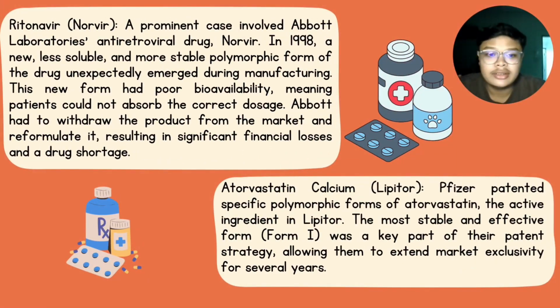Now, I will give the real-life examples. First, ritonavir. A prominent case involved Abbott Laboratories' antiretroviral drug, Norvir. In 1998, a new, less soluble and more stable polymorphic form of the drug unexpectedly emerged during manufacturing. This new form had poor bioavailability, meaning patients could not absorb the correct dosage. Abbott had to withdraw the product from the market and reformulate it, resulting in significant financial losses and a drug shortage.